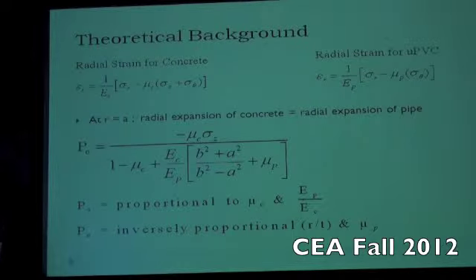And this expression could be limited down. This expression is a general expression for thick and thin-walled pipes. But for thin-walled pipes, it could be limited down to P naught is equal to 2 times the angular stress times the wall thickness divided by the diameter.